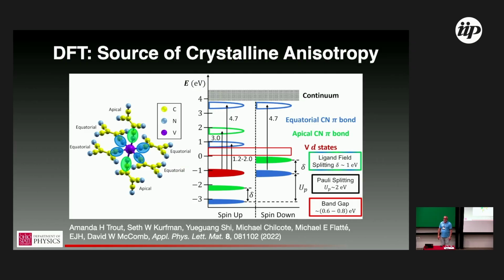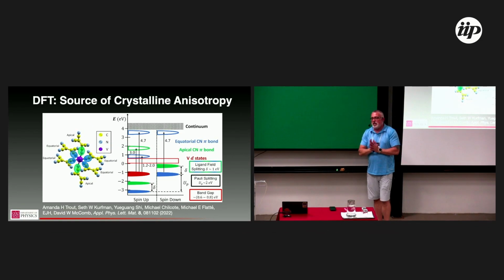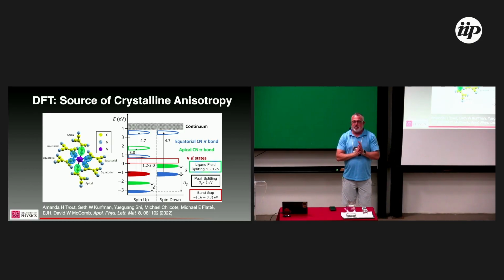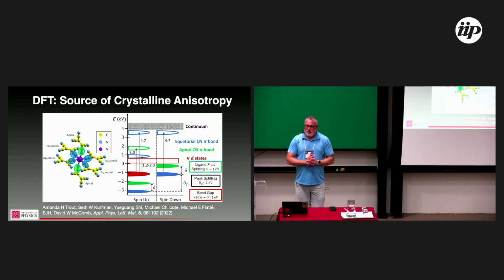Yeah, I think Mike has a question behind. Do any of the vanadiums exist with free electrons? Not that we can measure. These measurements are not super high fidelity, right? You're looking at sort of XPS type peaks, which have some noise on them. We don't see any indications of other oxidation states. But we do, as we talked about this morning, see evidence of two-level systems. So, for example, a vanadium 3+ could be contributing to the loss, and we might see it that way.